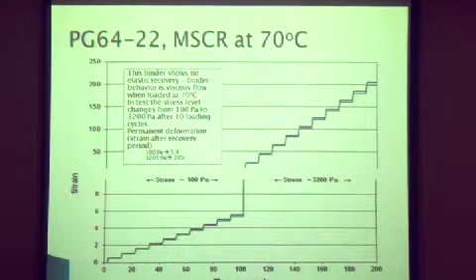Here I show an example, I have two different types of materials. This shows the results of a PG64-22, this conventional unmodified binder tested at 70 degrees. And here you can see stress of 100 pascals, here 3,200. You see the little load going on. When I put a load on, there's no recovery. I get strain, no recovery, strain and no recovery, strain and no recovery, and so on.